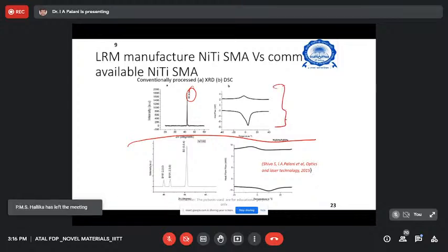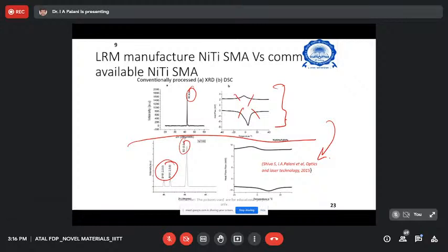So in the case of a DSC analysis, we can see an austenite start, austenite finish, and a martensite start and a martensite finish. So this is the one which we have fabricated using the setup. So along with the B2 phase, we could also observe some of the other phases which are available. And in addition to this, it is almost similar, only there is a mild shift, but still we could get a prominent identification of the austenite phase and the martensite phase.